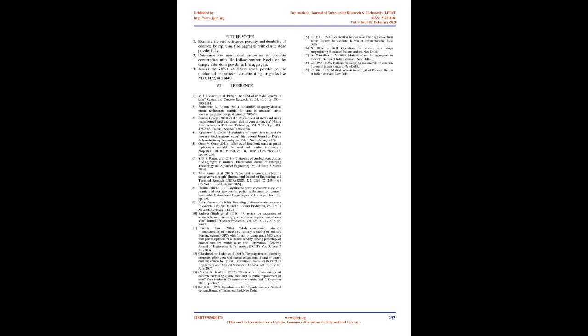Properties of cement. In this study ordinary Portland cement (OPC), 43 grade conforming to IS 8112:1989, was used. The specific gravity of OPC is generally taken as 3.15. The fineness of cement was 2.59.